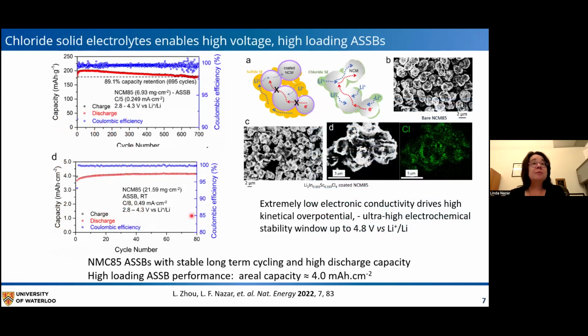So we carried out a lot of work on this material, and this is an example of its stability. These are cells under a little bit of pressure, but you can see that the cycling stability of these cells is really very good. This is over 700 cycles. We're getting almost the normal typical capacity we would get in a liquid electrolyte system from this configuration with good coulombic efficiency. And Lidong was able to increase the loading in these cells up to about 21 milligrams per square centimeter and achieve areal capacities on the order of 4 milliamp hours per square centimeter, again with excellent coulombic efficiency.